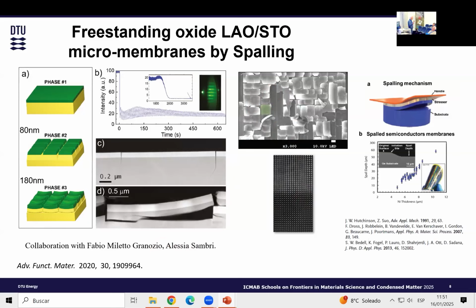The interface is still the same interface as we know if we grow LAO on top of STO, so everything looks the same. By the way, this type of spalling has been known for years in the electronics industry. This is the way they make a very thin layer of silicon. They put a nickel stressor deposit, and because of the stress, the material just detaches and forms a very thin layer of silicon. So it's not new what we're doing, but it is new for us when we first observed it. So we can see that the material is basically the same as if we grow it epitaxially on top of strontium titanate.